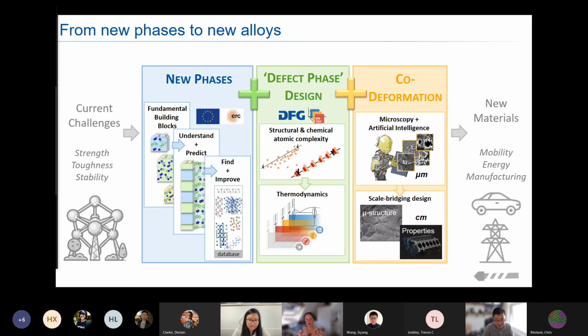And also your global composition is a rubbish parameter, right? Your global composition for an alloy that's a eutectic means nothing for a defect that sits in either of the phases. So after a lot of thinking, we went with the chemical potential, because that you can define for a range around the defect. If you at least anneal your sample to a certain extent, that's an environment around the defect. It doesn't have to be the entire sample.